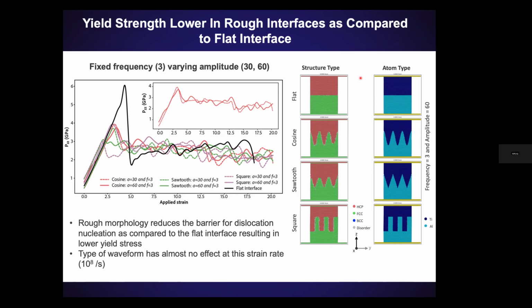So we ran our simulations, and I'm not going to show everything. I'm going to focus on 4 different types of interfaces. This is a stress strain plot that we extracted from molecular dynamics. Don't freak out about 6 GPa yield stress because remember the strain rate is really high, 10 to the 8 per second. And yield stress and strain rate have a linear relationship in general. And that's why that strain rate matters, because you have different deformation mechanisms. Also in molecular dynamics, you start with these perfect cells with no pre-existing defects. In reality, most materials have defects.